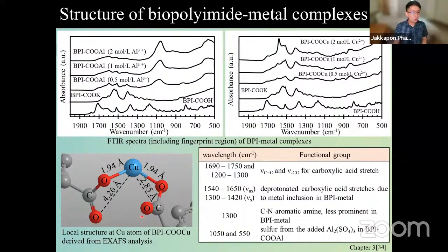I also do local structure studies for EXAFS analysis and see that copper is actually incorporated very well. The problem is in Thailand, we don't have enough energy for aluminum. So sad that I didn't do this for aluminum, but for the EXAFS, hopefully I can do it in the future. Okay, so here just the copper, but the aluminum one is working very much better. Okay, we will see that later.